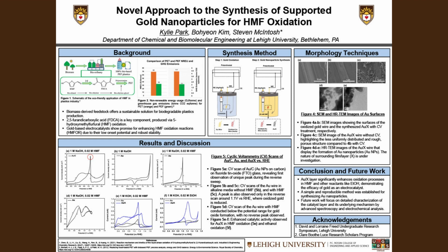A unique peak, circled in red, was observed during the reverse sweep of the CV, which suggests that there is a specific interaction between the gold surface and HMF that is only evident when the potential is reduced. This could indicate that there is some synergistic relationship between the reduction of the oxidized species on the gold surface and HMF oxidation. We wanted to see if the same phenomenon would occur for bulk gold, which is why we examined gold wire in the rest of the figures here, from 5b to f.